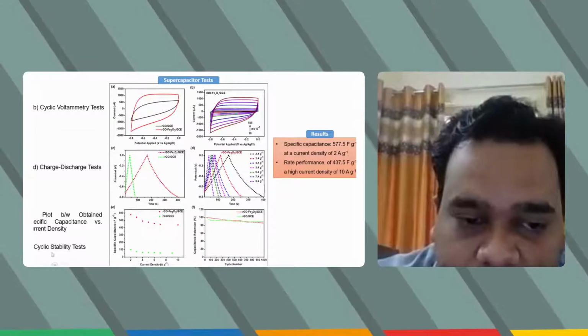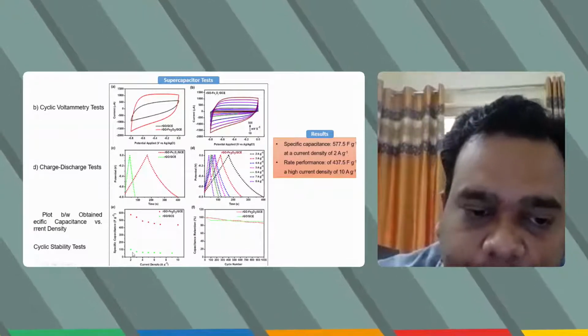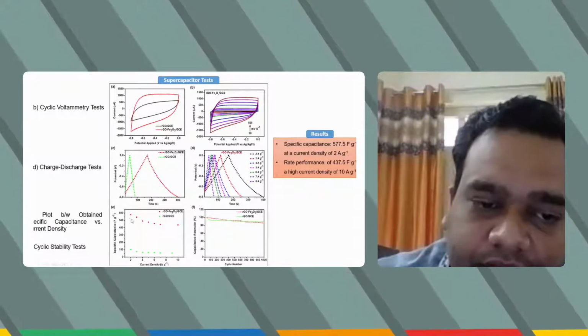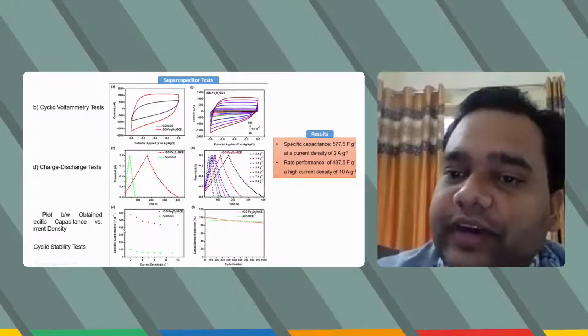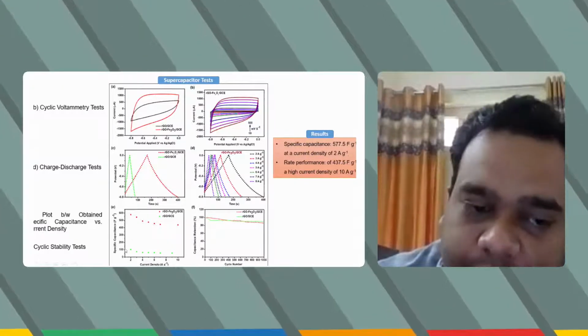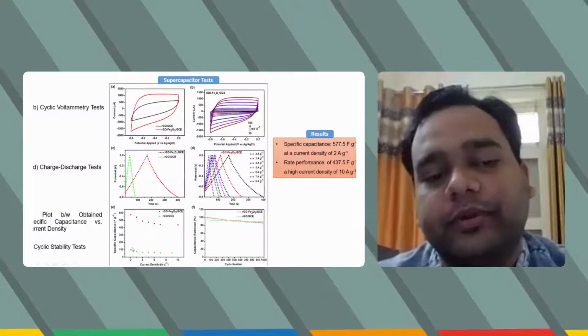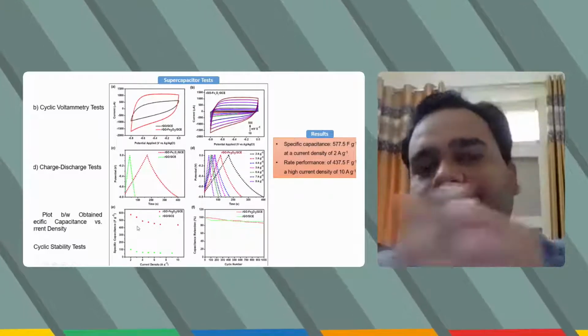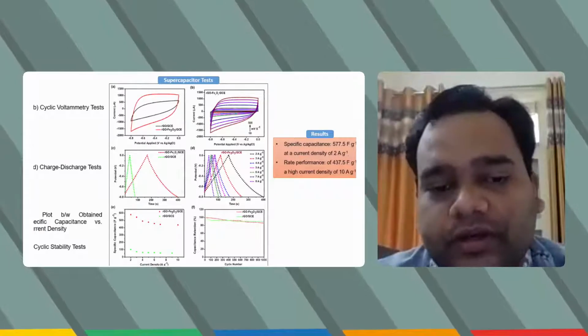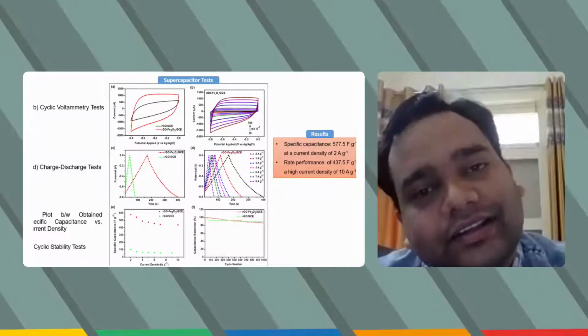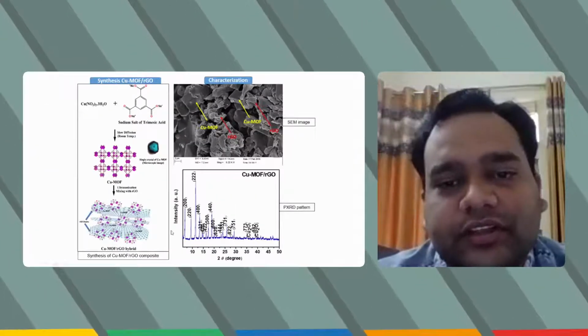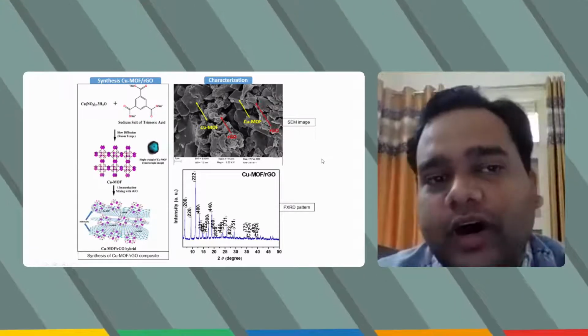So at a particular current density, you can see at 2 ampere per gram, this composite is exhibiting around 577 farad per gram, and RGO is exhibiting only 100 farad per gram. So that means there is synergy between Fe2O3 and RGO, which leads to a massive improvement in the specific capacitance. Similarly, we performed tests on various other materials, including these MOF RGO systems.